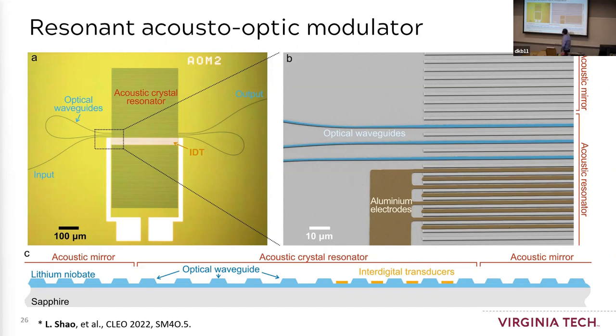So they can support acoustic waves, or if we do some band structure engineering, we can make very high Q cavities in the middle to enhance the interaction between the acoustic domain and the optical light. And for sure, we put down those IDTs, or interdigital transducers, to transduce the energy from the microwave to the acoustic.